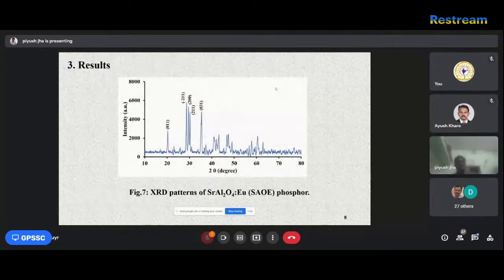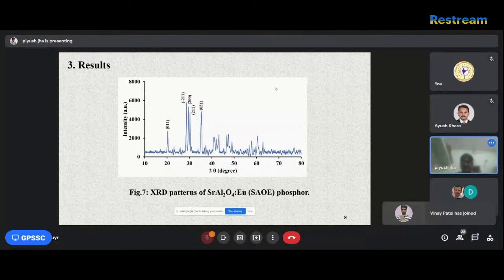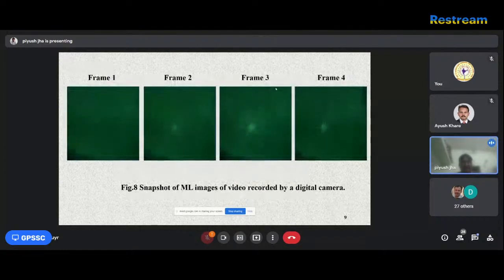Results. Figure 7 shows the XRD pattern of europium-doped strontium aluminate phosphor, and the peaks show the presence of a monoclinic structure of the sample. It is well matched with JCPDS card number 34-0379. When the ball impacts on the glass plate, it creates intense ML area at the center. Figure 8 shows the snapshots of ML images of the video recorded by the digital camera. Here we clearly see the fracture generation in the glass plate. In frame 1, no fracture is found. In frame 2, a small fracture is seen, and in frame 4, the final fracture image is found.